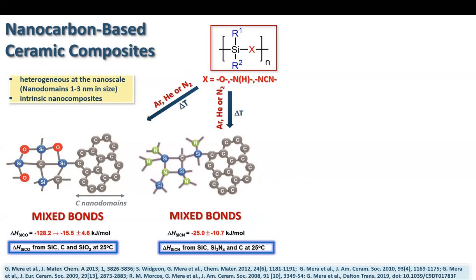So now, how can we do that? Generally, we know that the polymer-derived ceramic route represents the thermal decomposition in an inert or reactive atmosphere of a polymer to ceramic. On this slide, on the left-hand side, we have the polysiloxane transformed to silicon oxycarbide, and on the center side, polysilazanes transformed to silicon carbon nitride ceramics. Both of them have a mixed bond structure where silicon is bonded to carbon and to functionalized groups—oxygen or nitrogen—at the same time. Both are also composed of a free carbon phase of multi-layer graphene, and if we look at these structures, even if they appear as single-phase ceramics, they are actually heterogeneous at the nanoscale, composed of nanodomains of 1 to 3 nanometers in size. Therefore, we can name these ceramics as intrinsic nanocomposites.